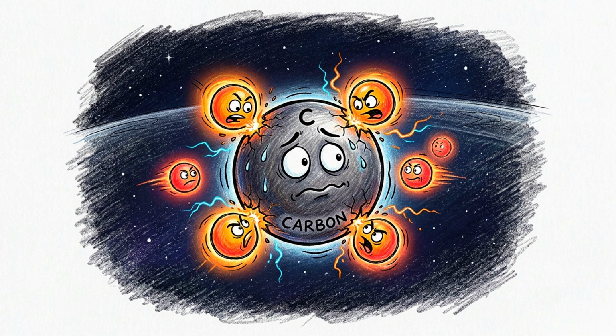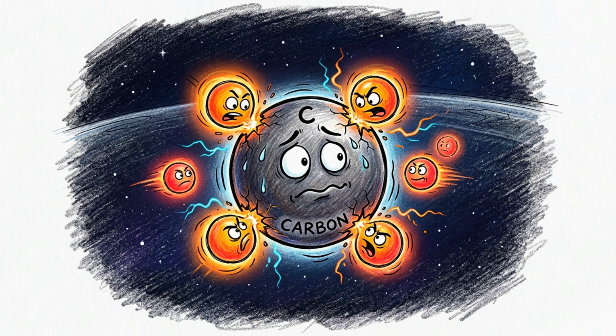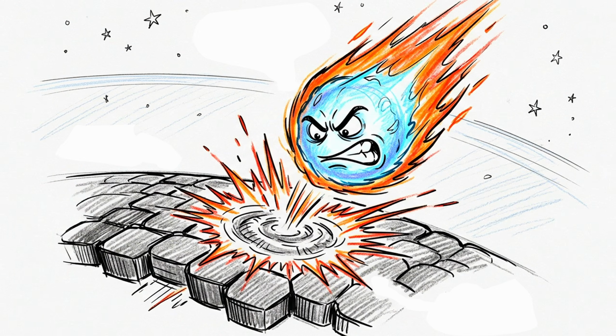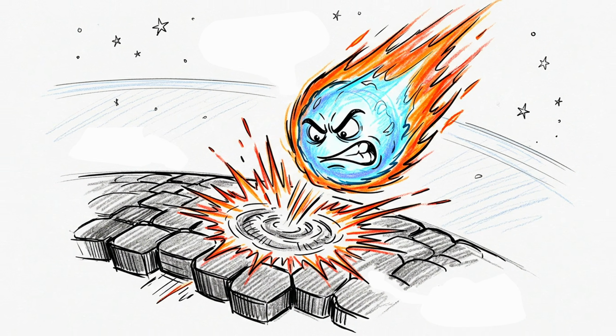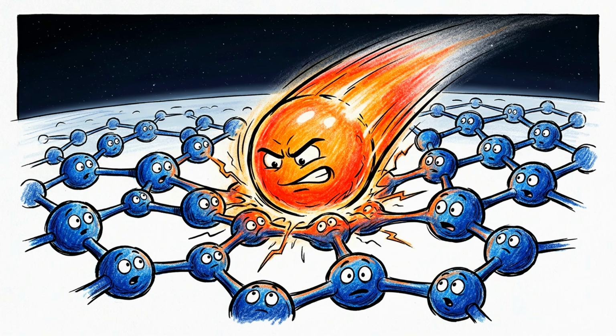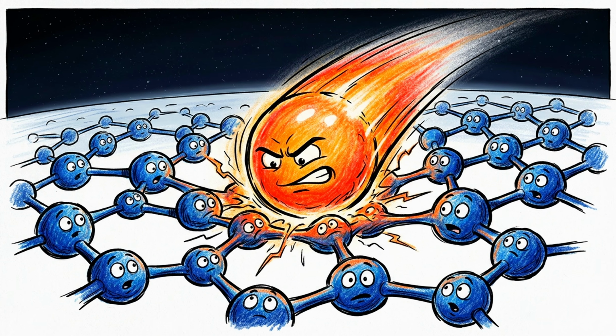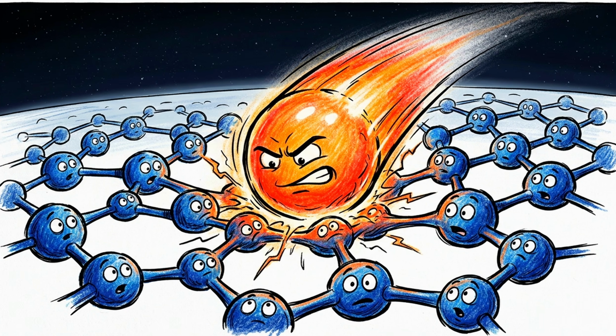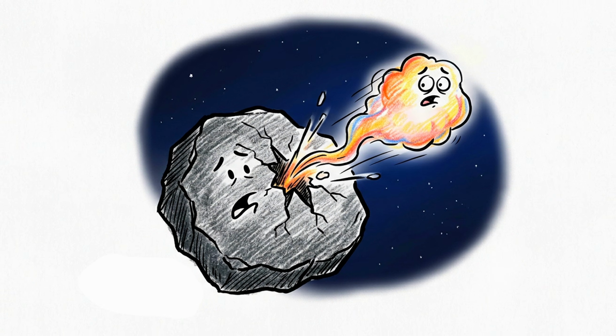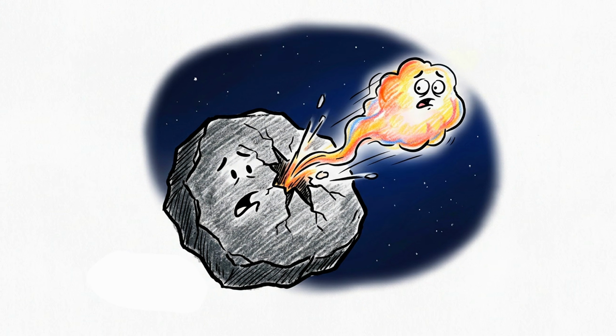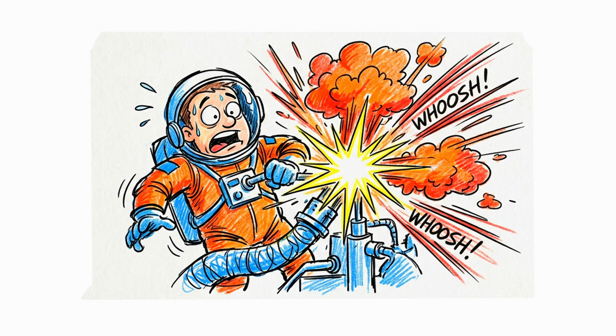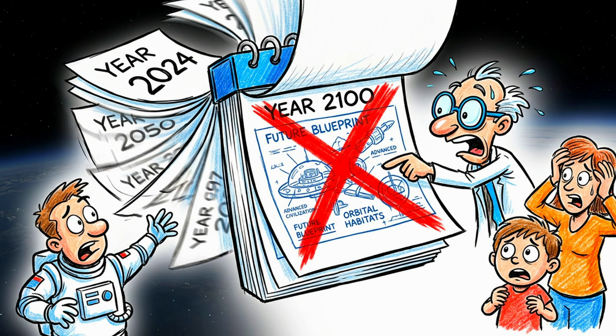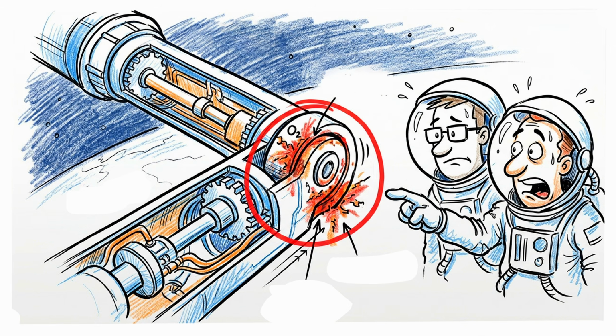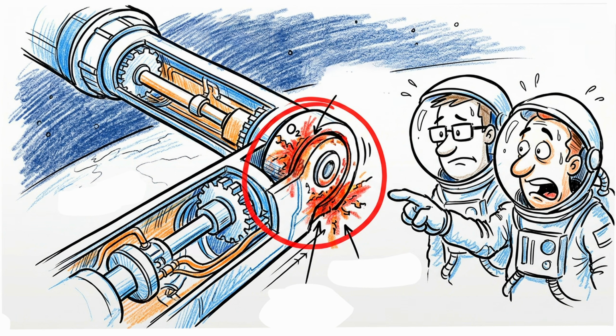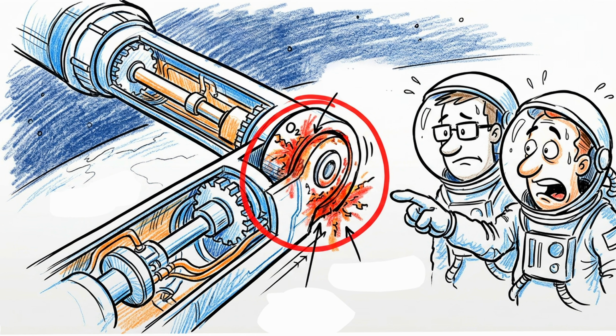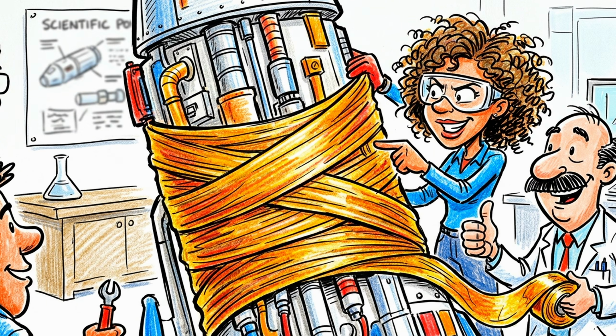The problem is that carbon is not chemically neutral in the atomic oxygen environment. Carbon is one of the substances atomic oxygen attacks most efficiently. When an oxygen atom at 8 kilometers per second impact velocity reaches a carbon surface, it does not bounce off. It oxidizes the carbon on contact, and the product, a carbon oxide gas, releases into space. This is not a slow process. It is not a long-term concern for future generations of engineers. It is the same reaction that happens at the most structurally critical point on the structure continuously from the first orbit after deployment. To make this concrete,